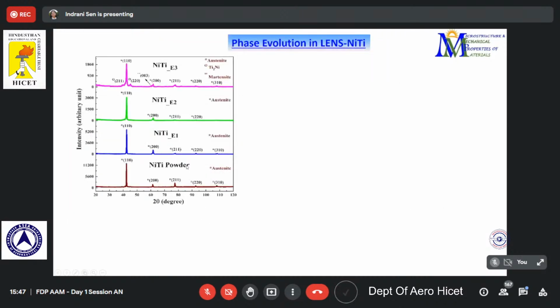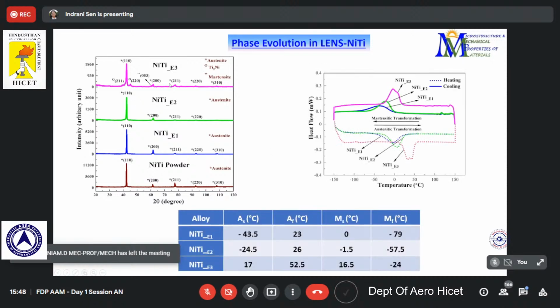Okay, in the XRD, we did the XRD for the starting powder as well as all these three additively manufactured alloys, and we can see that the one manufactured with the highest energy, as you have seen from the TEM, also shows the presence of precipitates and martensite phase. This is reflected in their DSC pattern, their phase transformation temperatures as well. The one prepared with the highest energy density shows a very high austenite finish temperature, which indicates that at room temperature it has the martensite phase.